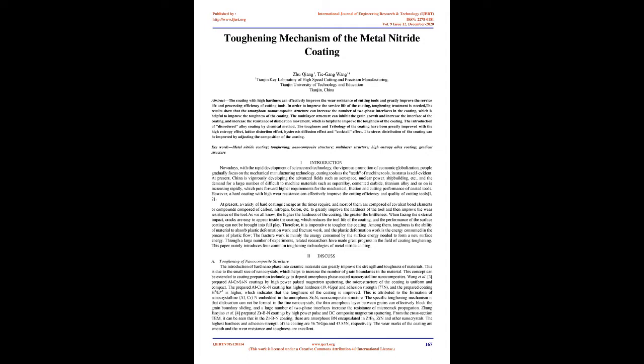The results show that the amorphous nanocomposite structure can increase the number of two-phase interfaces in the coating, which is helpful to improve the toughness of the coating. The multilayer structure can inhibit the grain growth and increase the interface of the coating, and increase the resistance of dislocation movement, which is helpful to improve the toughness of the coating.